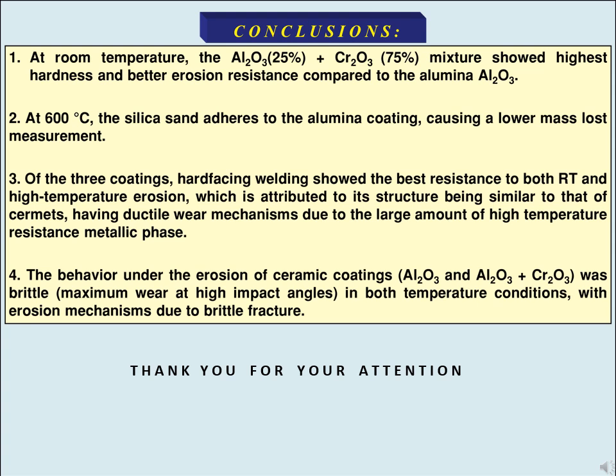4. The behavior under erosion of ceramic coatings, both alumina alone and the mixture of alumina plus chromium oxide, was always brittle. That means maximum wear at high impact angles for both temperature conditions, with erosion mechanisms due to brittle fracture.